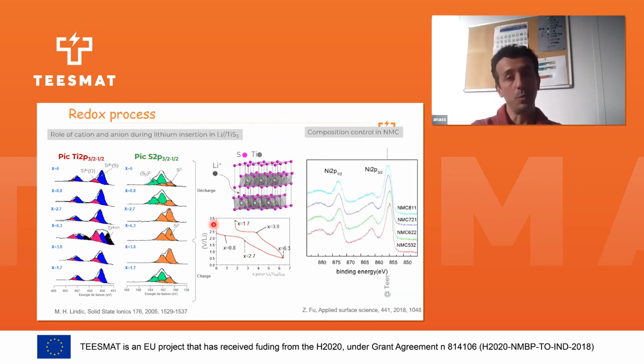And also nowadays with the NMC, XPS can help to quantify different grades of NMC. Like here I give the nickel peak in NMC 532. That means we have 0.5 nickel, 0.3 manganese and 0.2 cobalt, and so on. So here also the XPS can help for this kind of technology.